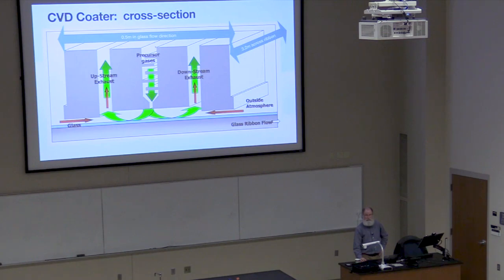So the basic idea is you feed gases in. Somehow you make sure they're all well mixed. Flow them onto the glass, and you exhaust out each side. So we might put 500 liters in, 500 liters in there, and exhaust 500 out there and 500 out there. If you put in 500 and take out 1,000, then the excess gas is going to come from in here. So you're going to suck in gas from the bath atmosphere. So everything goes out. You don't want any of those leaking out anywhere else.